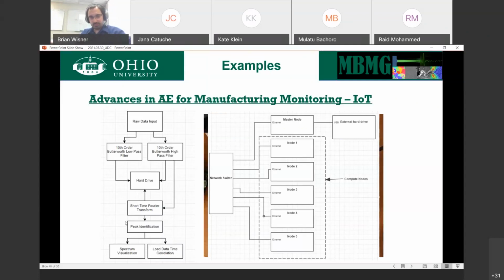So this left schematic is our current data flow process. We take the raw data, we filter it, we place that into a hard drive for storage because we want to make sure we don't lose data at this point. While that's happening, the hard drive can be reading into other systems that can do Fourier transforms, that can identify peaks, that can do different plotting, that can potentially do outlier analysis. We can keep adding to this flow, but this is the current scheme. This is done using a cluster of microprocessors. In our case, we're actually implementing Raspberry Pis. The premise is this external hard drive is our link between our data source and the processing itself. So as the data is collected, it's periodically dumped into this drive to be immediately processed.